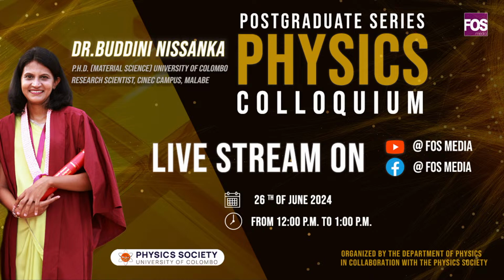I have a question about graphene oxide in general. Is reduced graphene oxide more similar to the original graphite? No, it is different from graphite, because if you see the XRD spectra, graphite has a sharp and intense XRD peak. That shows the crystalline structure of the graphite. But reduced graphene oxide has an amorphous structure, which shows broader diffraction peaks with low intensity.